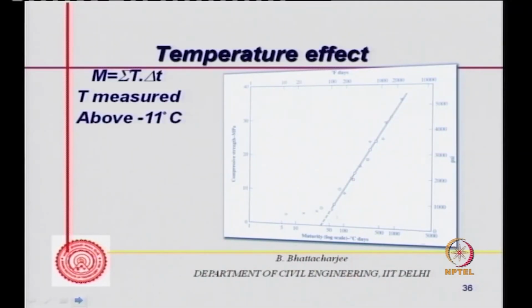Now we talk in terms of something called maturity, the temperature effect. What has been seen is that if temperature T1 is maintained for time delta T1, T2 for delta T2, and so on, and you sum this up, this is what is called maturity. It has been seen that maturity, on a log scale in degree centigrade days, versus compressive strength can be linearly related. So higher temperature for less time will give almost the same effect as lower temperature for a longer period. That's the idea, and that gives you the idea about steam curing.